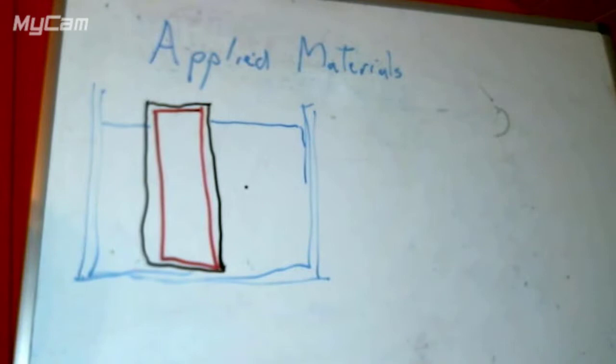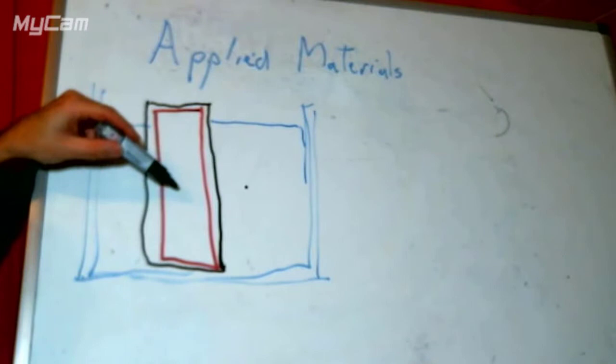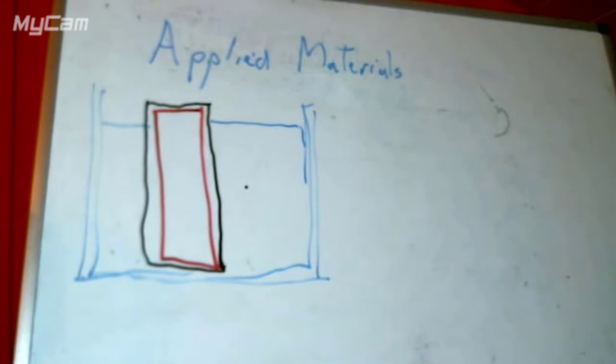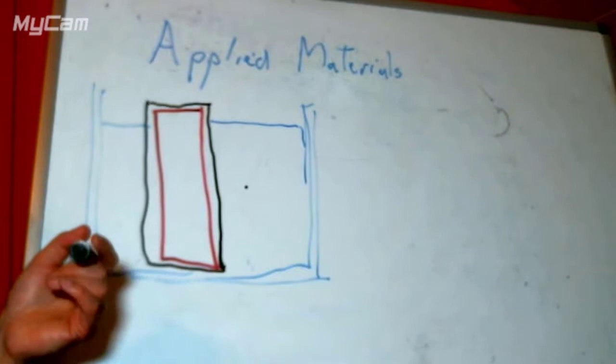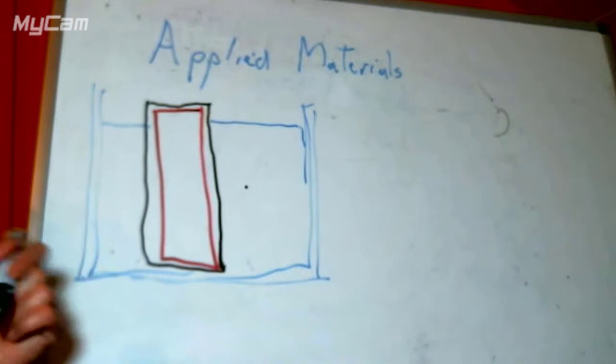In normal life: if this is tap water, pretty much nothing will happen — our aluminium is going to sit there and do nothing. If it's seawater it will corrode, not super fast but it'll corrode. If it's the inside of a dishwasher, which is highly basic water, it will go black and corrode away fairly awfully. If it's acid it will also corrode very quickly. So we can see there's going to be some kind of pH-dependent reaction.